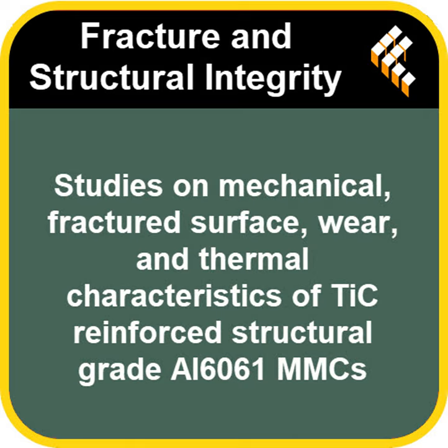And what were the numbers for this increase? How much better did it get? The maximum thermal conductivity measured for the Al6061 plus 9 wt% TiC-Co composite was 194.0256 watts per meter degree Celsius, which is significantly higher than the base Al6061 material, which was around 166.9845 watts per meter degree C. That's a decent jump. Better heat dissipation. Definitely. Suggests improved performance in heat-sensitive applications.